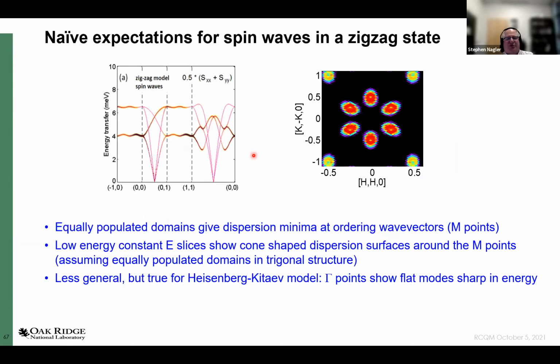So let me consider what these will look like for a zigzag state. Now, in fact, it depends on the details of the Hamiltonian. Various different Hamiltonians can lead to zigzag states, so I'm just picking one. What will happen here is that I will have dispersion that comes down to 0 at something equivalent to an ordering wave vector, or M point, in this 2-dimensional model. And typically I will have equally populated domains. So I will see something with a 6-fold symmetry, and each one of these points is effectively a spin wave cone around an ordering wave vector. Okay, so that's sort of typical of what happens.